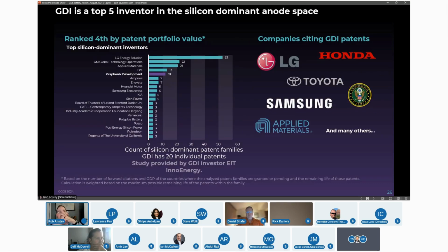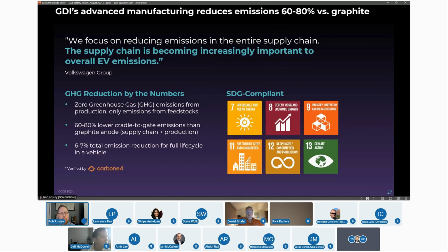And we have patents that protect this technology very broadly. We have 20 individual patents, 12 patent families. We were independently validated as 4th in the world for patent families in silicon dominant, and we were cited by some of the leading high energy cell companies and OEMs. We also decrease greenhouse gases by 60-80% as validated by Carbon 4. So this will be much more environmentally friendly than graphite anodes will be.